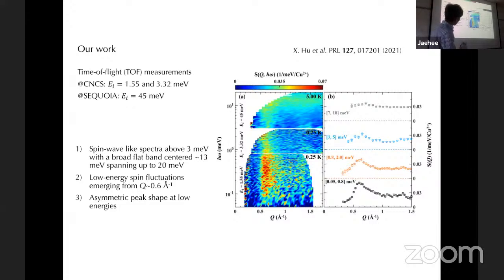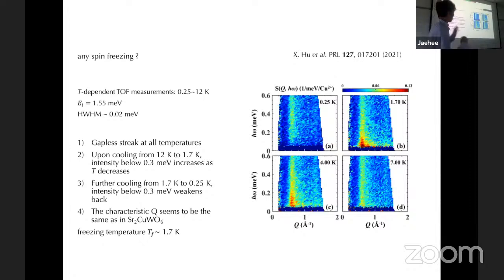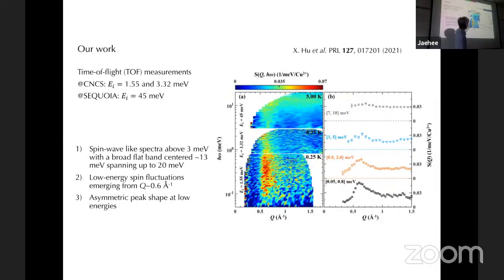And then here is a constant energy cut as a function of Q. At high energies, this is powder, so powder averaging gives an upper peak, but at very low energies you can see this asymmetric shape. So when you see these asymmetric features in a powder sample, then we immediately know that the magnetic excitations are low dimensional because it's due to powder averaging. I'm not going to go into detail, but anyway, now we focused on very, very low energies here as a function of